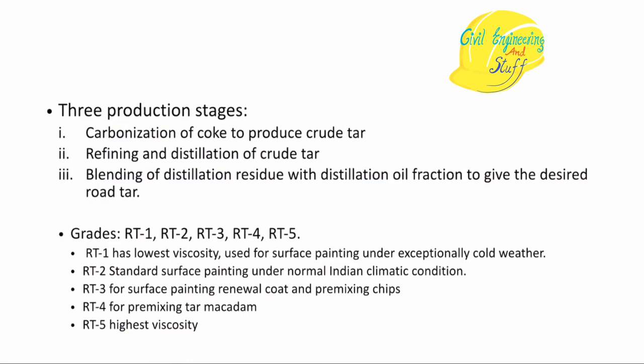Tar is graded as RT1, RT2, RT3, RT4, and RT5, where the numerical value represents viscosity grading. RT1 has low viscosity and is used for surface painting under exceptionally cold weather. RT5 has the highest viscosity. For Indian climatic conditions, RT2 is used, while RT3 and RT4 are used for surface painting renewal works and premixing respectively.